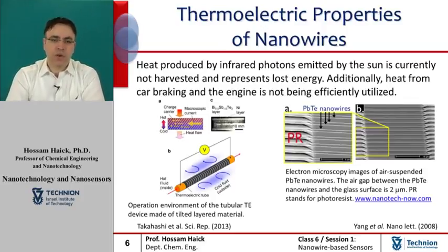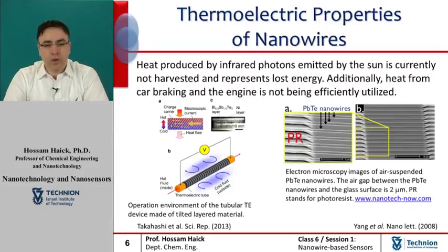The presented image relates to a stoichiometric and single-phase lead telluride nanowire array that has been prepared using photoresist bottom-up lithography and patterned with an electrodeposition technique. This fabrication approach has been evidenced to provide control over the wire width and thickness and the suspension of the nanowires across 2 micrometer air gaps.